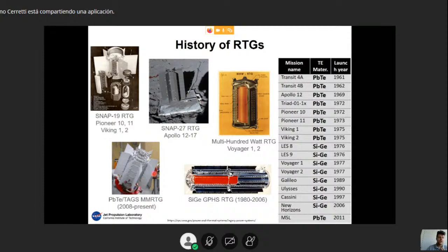As you can see, the shape resembles a lot the one of the SNAP. The same design has been used, but the technology inside, the material, is completely different. And as you can see here from the table, most of the material that has been used over time, from 1961 until 2011, is a mix of lead telluride and silicon germanium based material.